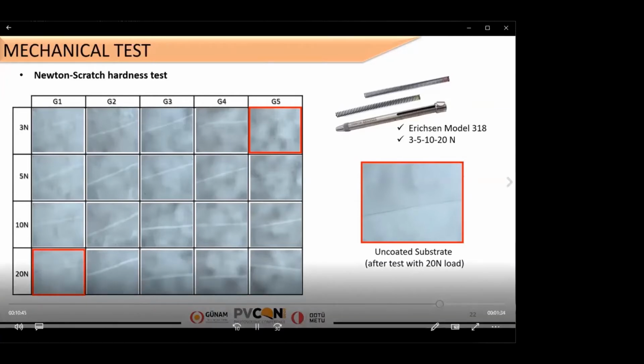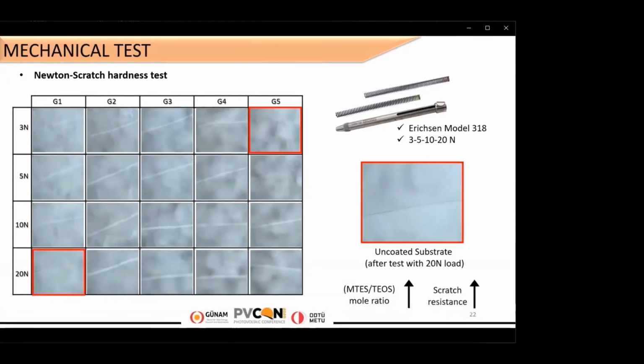Here's another mechanical test that is called Newton's scratch hardness test. You can see the scratches on the surface of coatings after the test in the figures. The columns represent versions of solutions and rows represent different loads. It doesn't seem that there are any scratches on the G5 sample after 3 Newton loads. And then we look at even the uncoated substrates after 20 Newton load, we can see scratches of glass as a black line. This type of scratch only appears in the G1 sample, not in the others. So we can say that the scratch resistance increases with increasing MTES ratio.